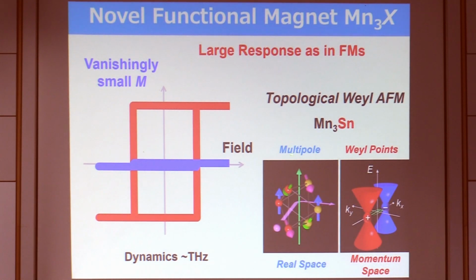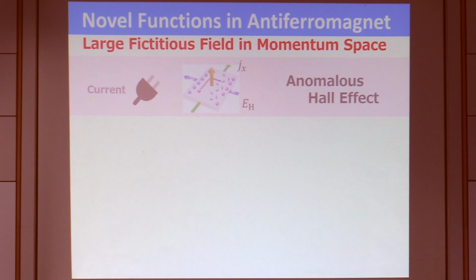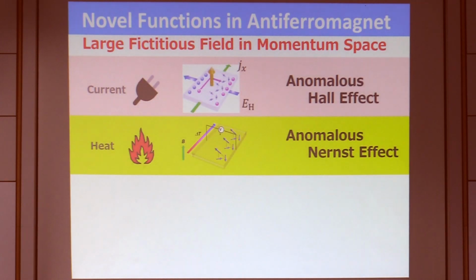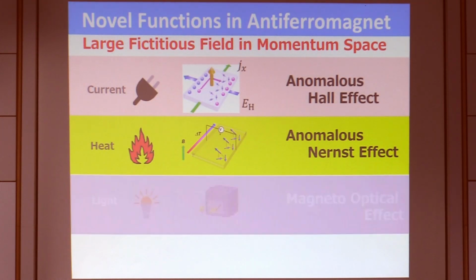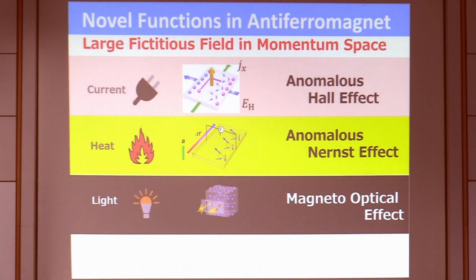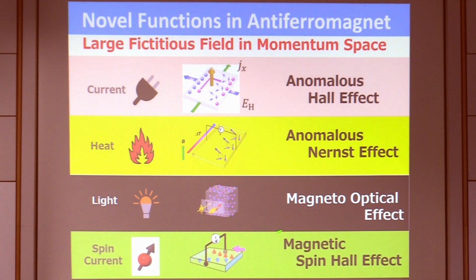One is, as we have heard, the multipole component realized in the real space magnetic texture. The other is the Weyl semimetal aspect, which is realized in momentum space. This combination is quite important to realize something which has never been seen in antiferromagnets until recently. So anomalous Hall effect and Nernst effect, which have already been nicely introduced in the previous talk, and magneto-optical effect. And we also show the spin Hall effect.